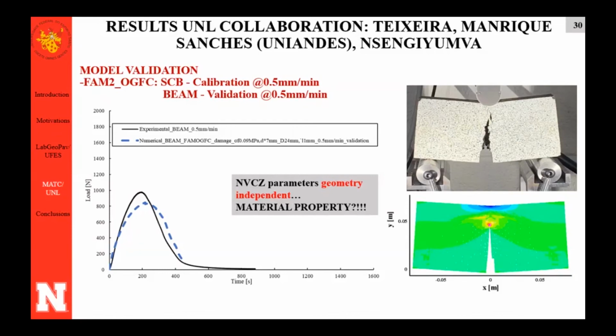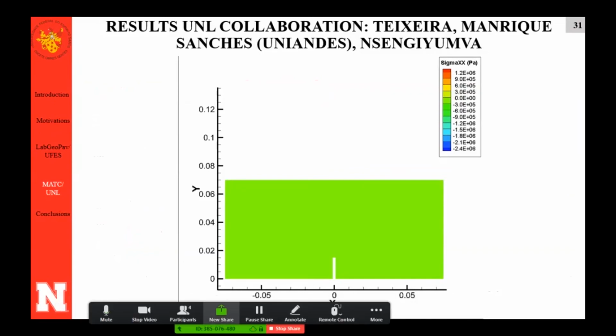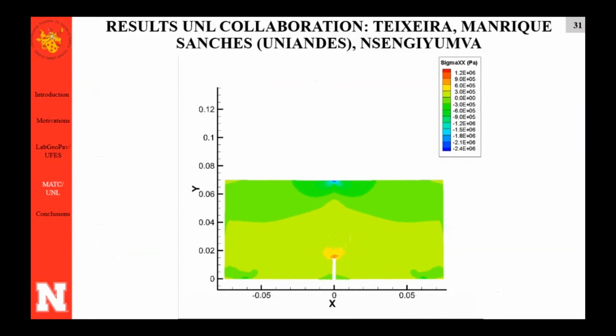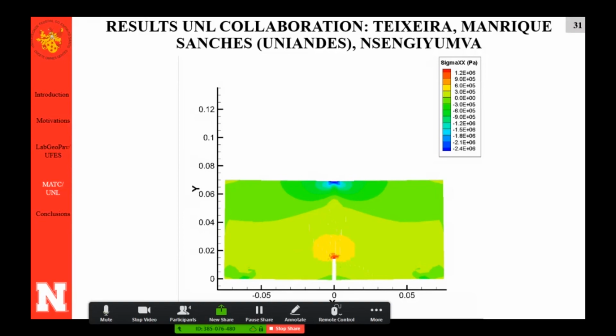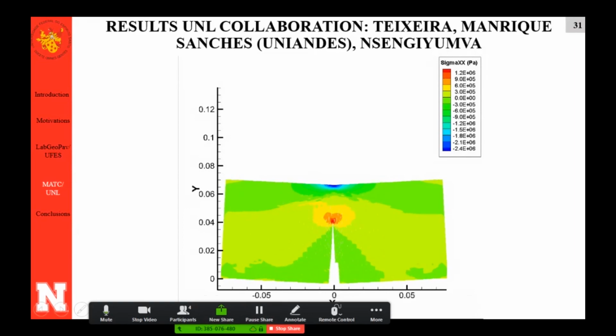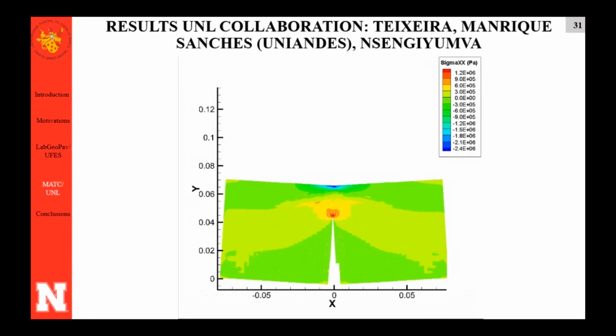I brought to you to show those interesting results. And again, the contour plots seem quite reasonable. The way that the crack starts and how it propagates is reasonable with what we observed in the laboratory. This one is going slowly, so let me just move forward. So you can see this test is done at 0.5 millimeter per minute. It's a really slow test, but you can see the crack propagating at the center as we expect. So those are the results that I could get.